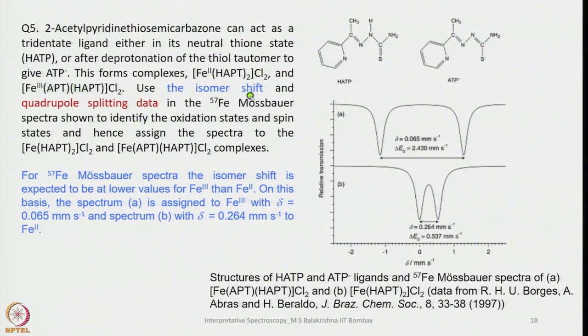So use the isomer shift and quadrupole splitting data provided in the 57Fe Mössbauer spectra and identify the oxidation and spin states, and hence assign the spectra to the complexes here. For 57Fe Mössbauer spectra, the isomer shift is expected to be a lower value for Fe3+ than Fe2+.